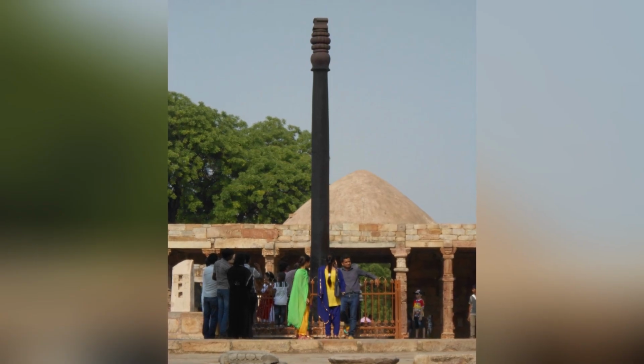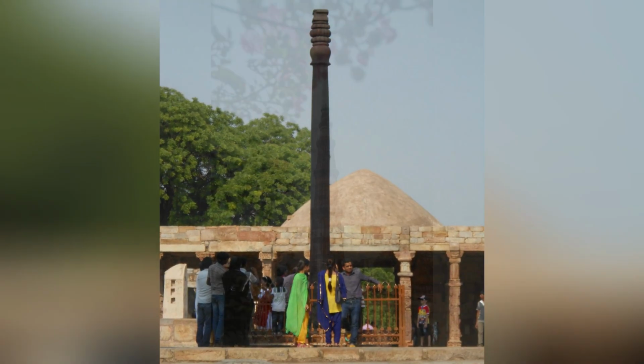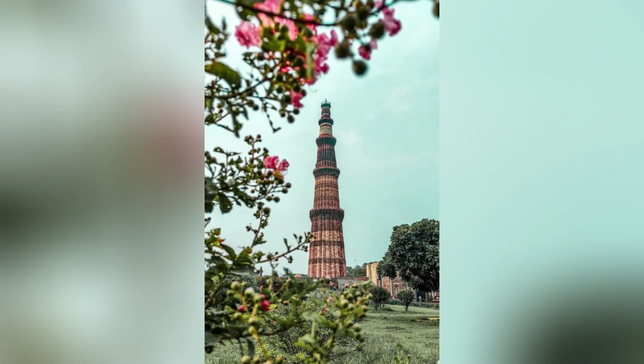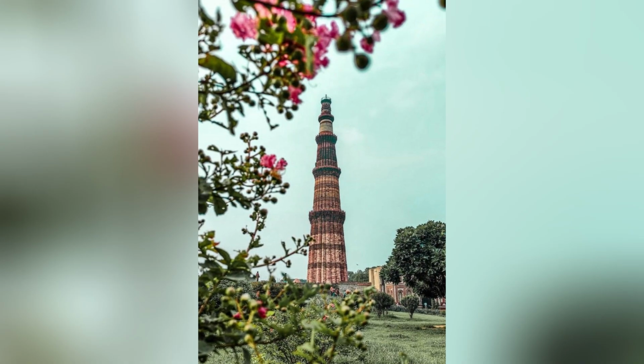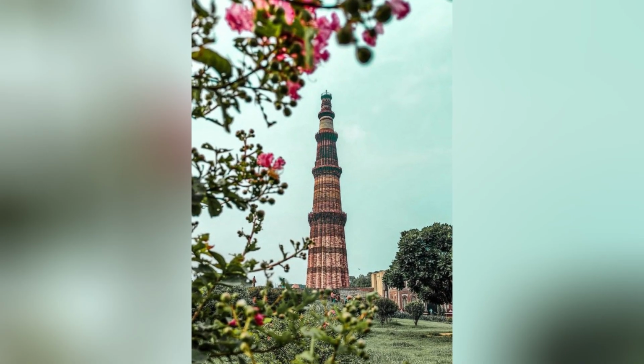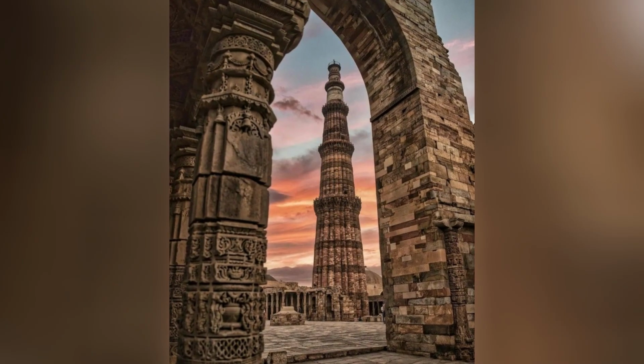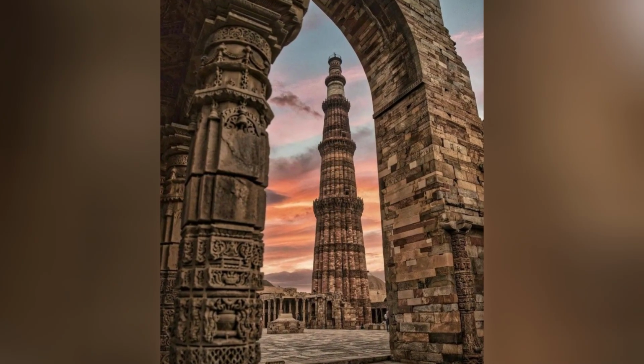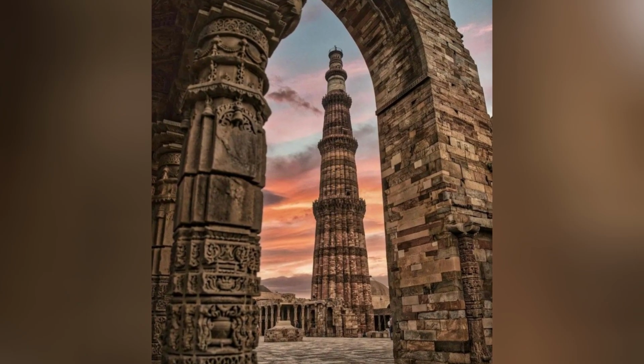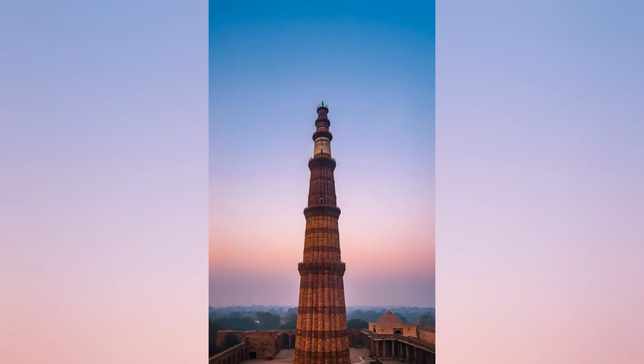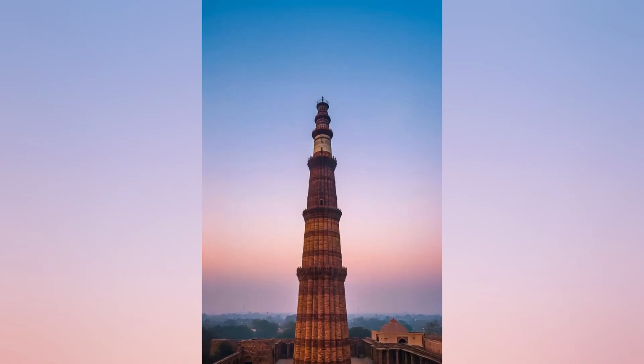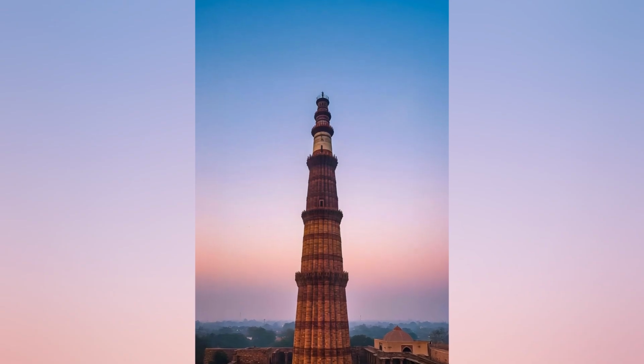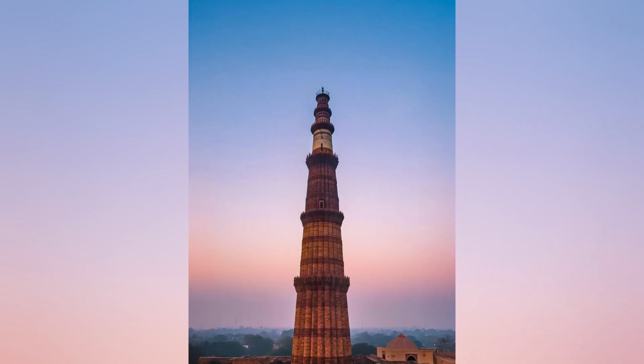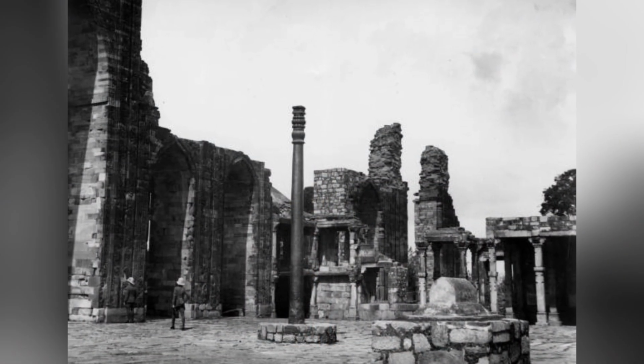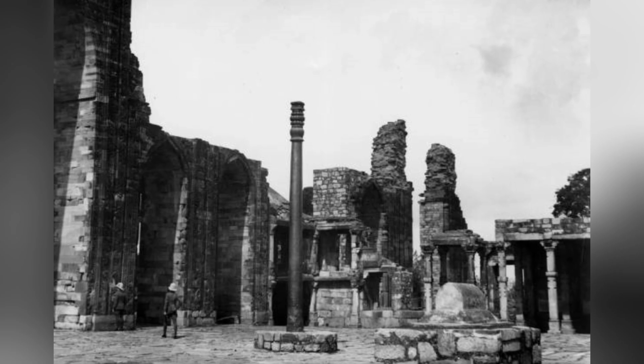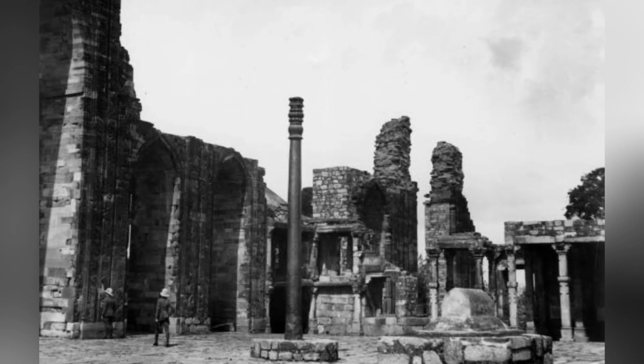The fifth major track of investigation has been the attempt to reproduce the corrosion resistance of the Delhi pillar's iron using modern metallurgical techniques. Several research groups have produced experimental iron alloys with compositions that are similar to the Delhi pillar's iron, including a high phosphorus content and a low carbon content, and they have tested the corrosion resistance of these alloys under simulated atmospheric conditions. The results of these experiments have confirmed that the high phosphorus content is the key factor in the corrosion resistance, with phosphorus-rich iron alloys consistently outperforming phosphorus-poor iron alloys in corrosion tests.